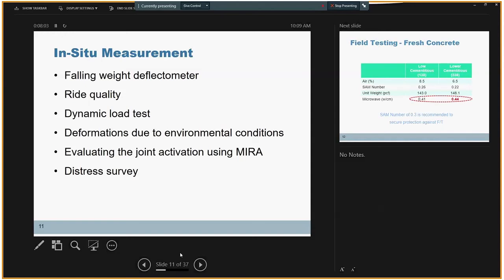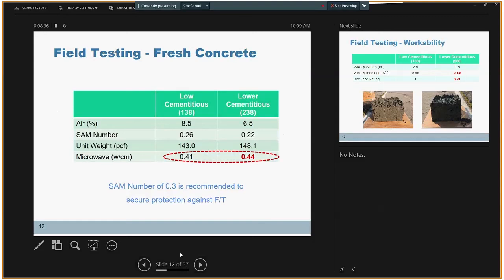And the third category of the data we had was data from sensors embedded in concrete pavement, and data about in situ measurement, falling weight deflectometer, ride quality index, and data from testing the pavement sections exposed to controlled traffic loading, and also data from embedded sensors that capture the effect of environmental conditions on these concrete pavements. Also, activation of the joints and monitoring the distress in investigated cells.